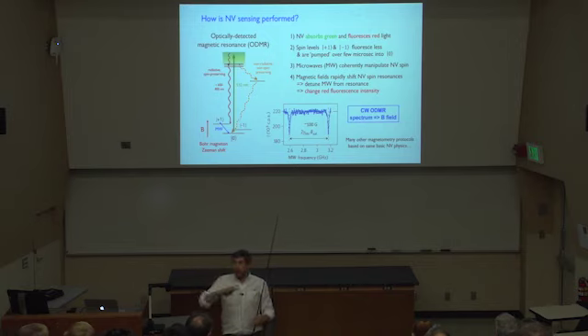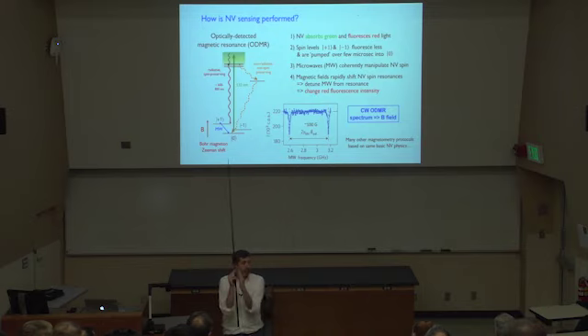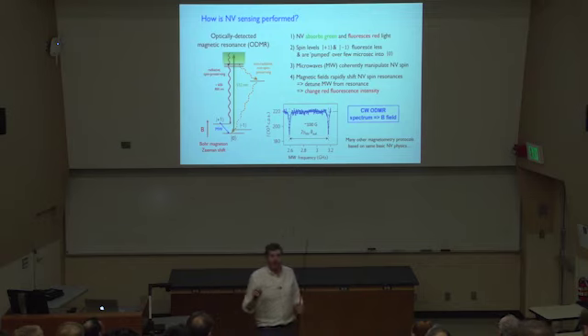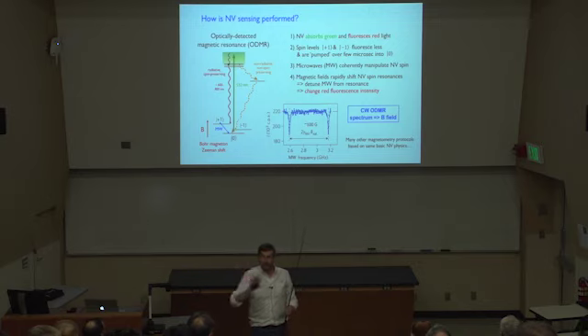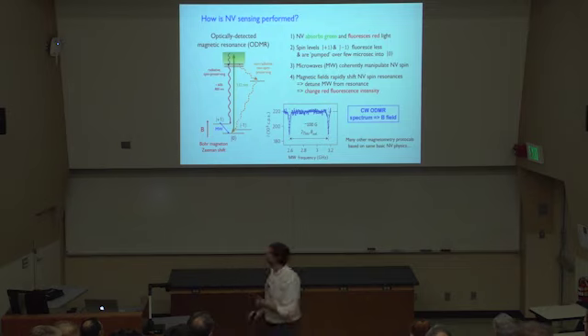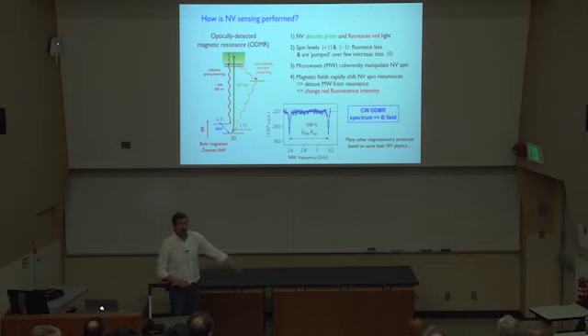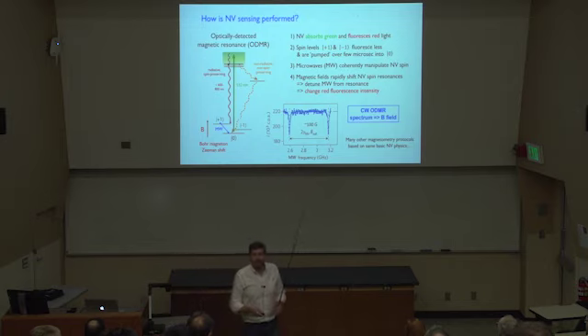This is for static magnetic fields, a magnetic field that's just external here, just static. There are time-varying magnetic fields, complicated broadband time-varying magnetic fields that are of interest in some experiments. Some are narrowband magnetic fields, like fields that come from NMR signals in some experiments. You wouldn't use this technique of scanning through and doing the spectroscopy for those different examples, and we have different experimental protocols that I'll only lightly touch upon when it makes sense for measuring those different types of fields, but they all, in the end, depend upon these same physical properties that are listed here: that the average fluorescence rate depends upon which spin state you're in, that you can optically prepare the spin state, and that with near-resonant microwaves, either pulsed or continuous, you can manipulate the spins. Okay?